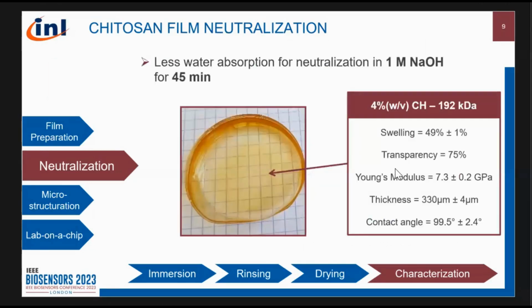So this is why we started using the concentration of 1 molar of sodium hydroxide, where we left the film in this solution for 45 minutes. Now we obtain a swelling of 49% with the same transparency as before the neutralization, with a slightly higher Young modulus and a thickness of 330 micrometers. We also have a hydrophobic contact angle of 99.5 degrees.